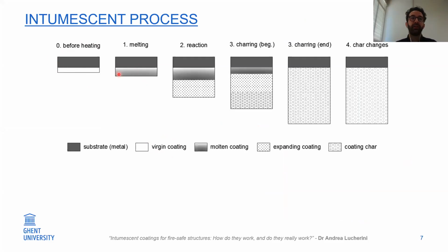Then when it's exposed to heat, the coating starts melting, and the melting starts releasing gases. The gases are trapped in the molten coating, as you can see here. This is called the reaction stage. Then the coating starts charring at the surface, and the char progresses towards the back of the coating. And finally, we have char changes. In particular, in an oxygen-rich environment, you can have oxidation of the char. You can clearly see this in the color change, from a black, dark char into a white one, which is oxidized at the surface.